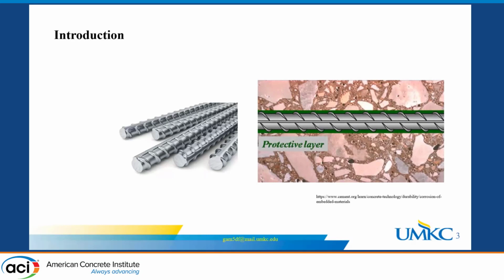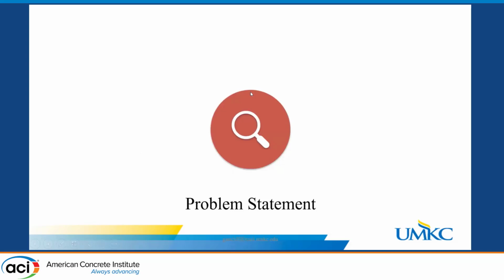That's why we are using steel. Once we embed steel reinforcement in a highly alkaline medium such as concrete, which has a pH of more than 12, the steel reinforcement thermodynamically generates a protective layer, an iron oxide layer, around the steel. As long as the pH of concrete is high and the protective layer, or passive layer, is there, the structure is in an immune condition, and everybody is happy because nothing is happening in that situation. But there is always a problem.